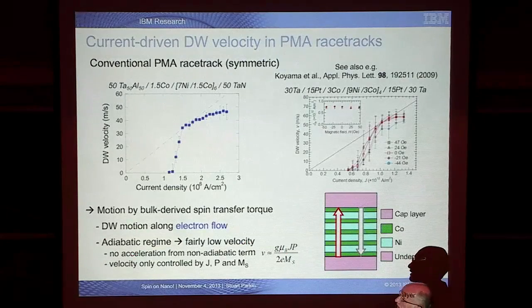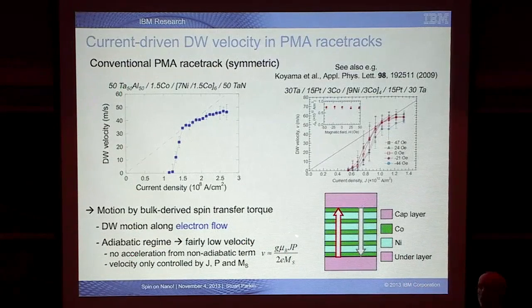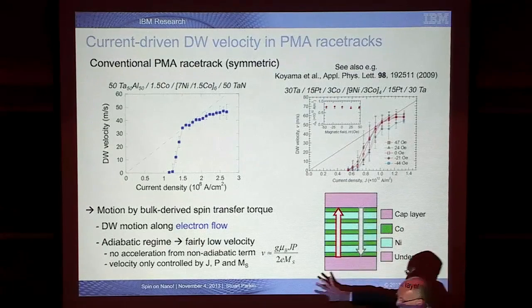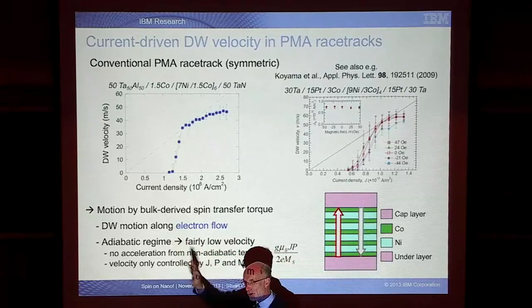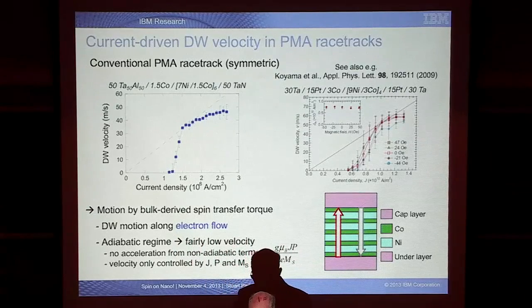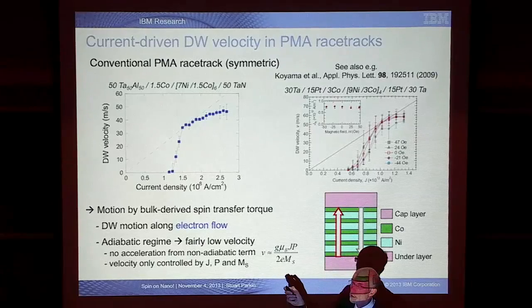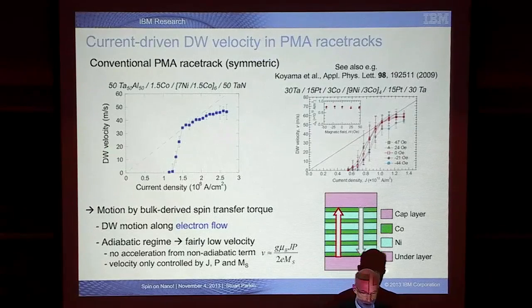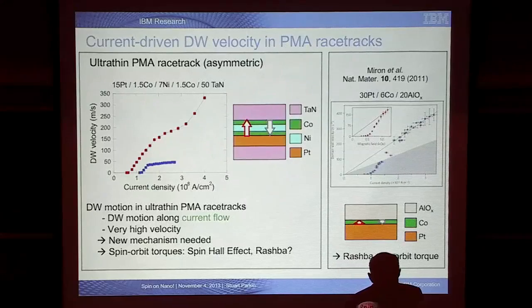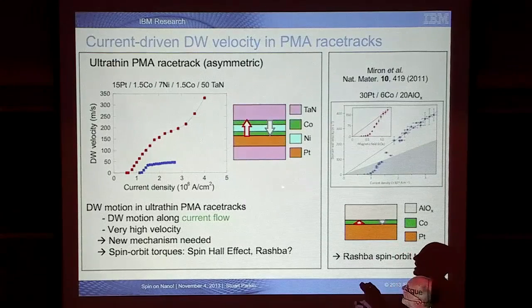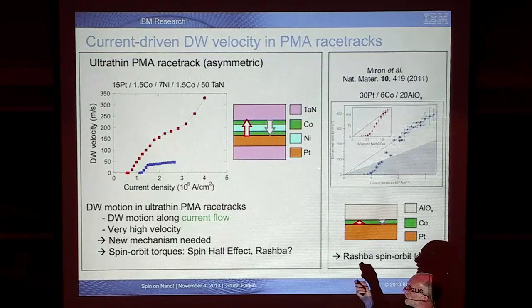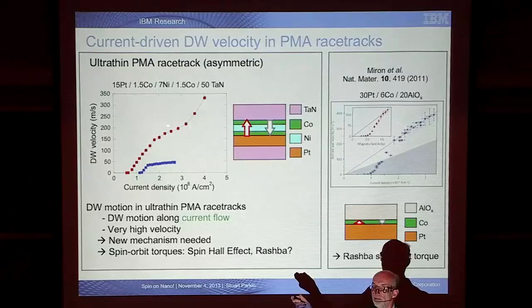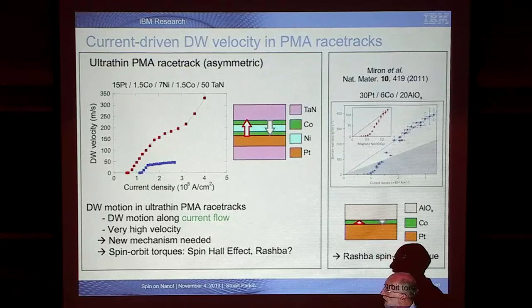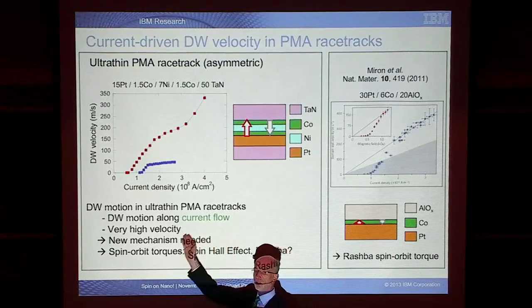And now if we look just briefly at the velocity of domain walls as a function of the density of current, then in conventional materials like this, the domain walls move along the electron flow, as I mentioned, along the direction of the flow of spin angular momentum, at velocities of the order of 50 meters per second for reasonable current densities. Now, what was discovered just 3 years ago was that in ultra-thin, perpendicularly magnetized materials, which are grown on heavy metals like platinum, the domain walls move much faster, 5 or 6 times faster for the same current density, and they move in the wrong direction. They move in the direction of current flow.